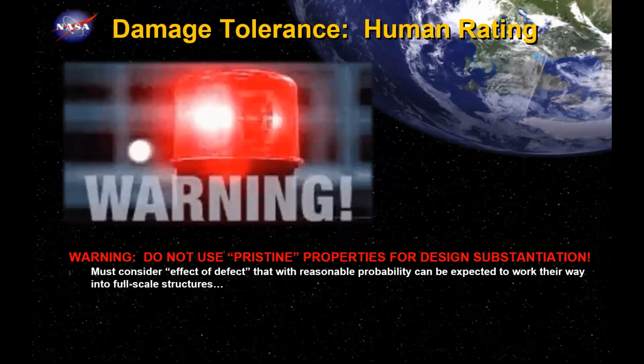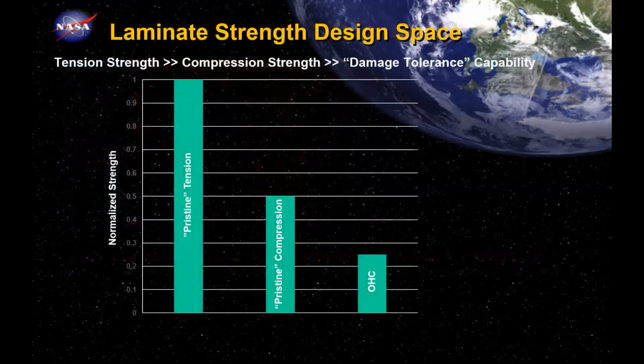I honestly believe that structures, not just those that are human rated, need a careful strategy to interrogate the effect of defects and damage that can really be in the structure. We call it worst case credible, or NASA now uses a term called the residual threat determination, the RTD. The idea is that you think through very carefully what are all the sources of defects from any source through time, and you design a test campaign that interrogates the effect of defects. In that way, this idea of pristine properties becomes almost irrelevant. It's only really necessary for stiffness-driven calculations like modulus and Poisson's ratio. But for strength, we need to get into damage tolerance.